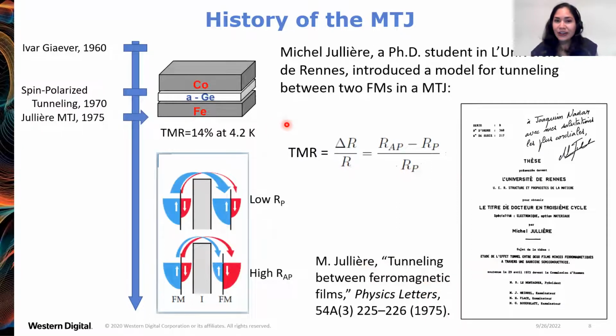Then a few years later, in France, there's a PhD student, Michel Jullière, and he was inspired by the work of Meservey and Tedrow. He had met them at a conference in Europe, and for his thesis work, he introduced a model for tunneling between two ferromagnets in a magnetic tunnel junction. He proposed iron and cobalt ferromagnetic electrodes separated by a thin insulating tunnel barrier. Tunnel barriers are just 1 to 2 nanometers thick. And he used this tunnel junction, a magnetic tunnel junction, in an experiment as well.